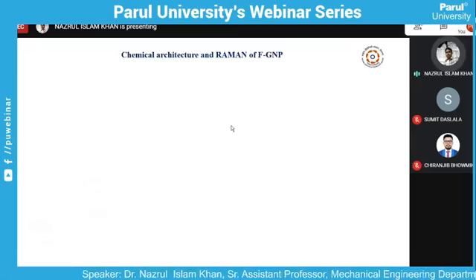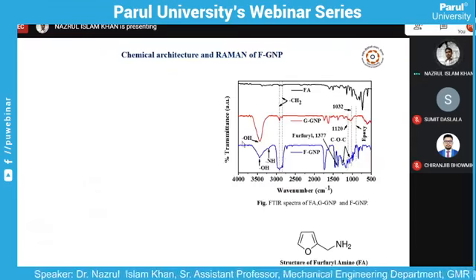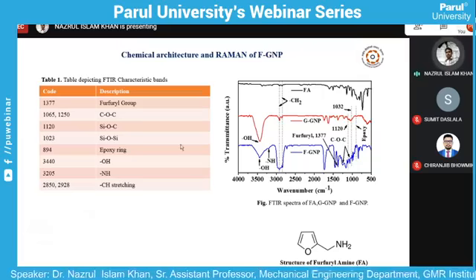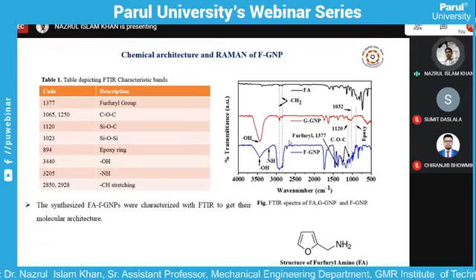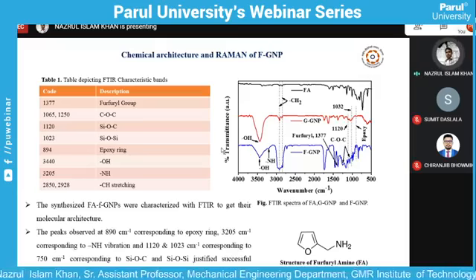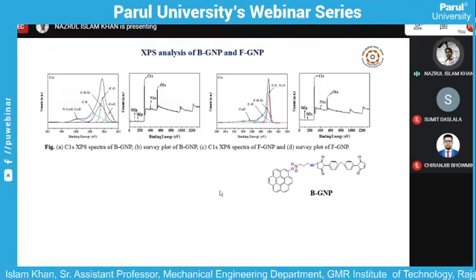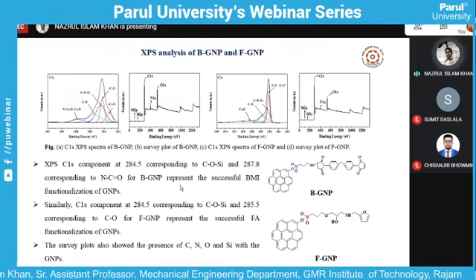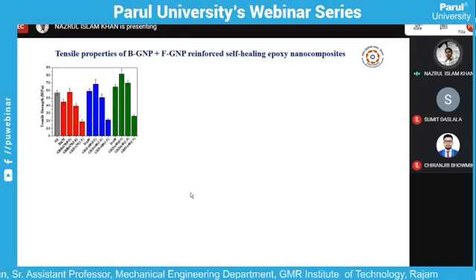So we need to functionalize graphene with both the diene as well as dienophile part. That's why first we functionalized with furfuryl amine and we checked the chemical characterization and found that yes, functionalization has taken place. We also did the XPS analysis and found that yes, surface functionalization has taken place.